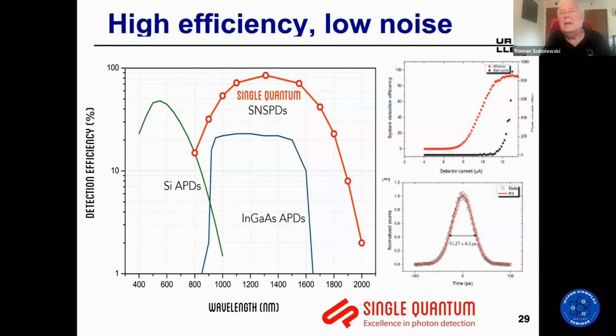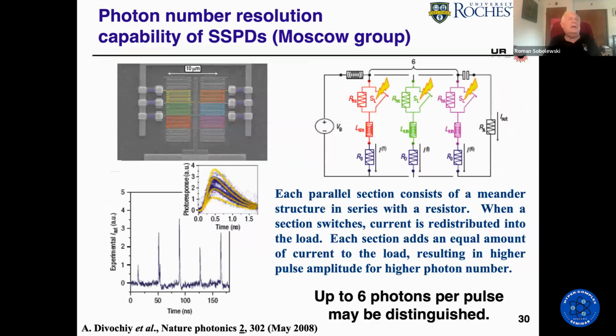So this is really a dramatic jump forward compared to semiconductor devices, which were essentially kilohertz type devices, and again with quantum efficiency, you can see 20%. Detectors, if they are made into multi-pixel arrays, can detect several photons under the assumption that two photons are detected only if they don't hit the same detector. So you can see this is 1, 2, 3, 4, 5. This is a 10-pixel detector, and experimentally it would work nicely to time resolve up to six photons.